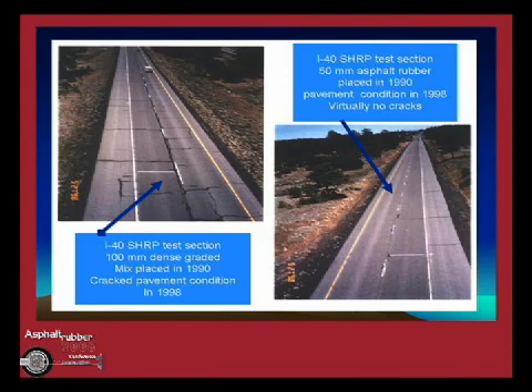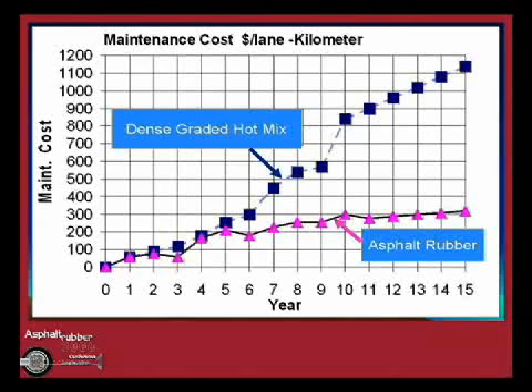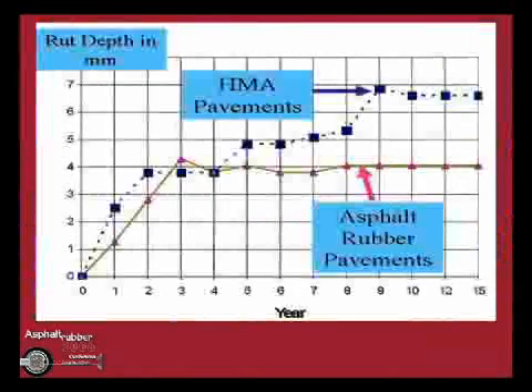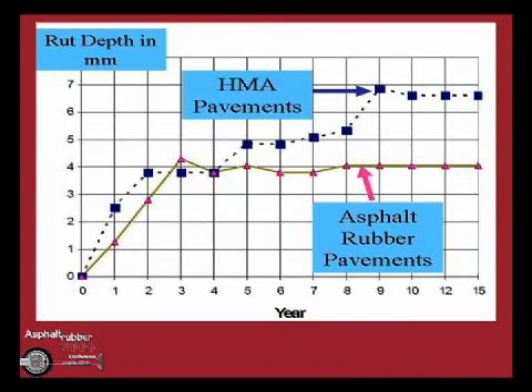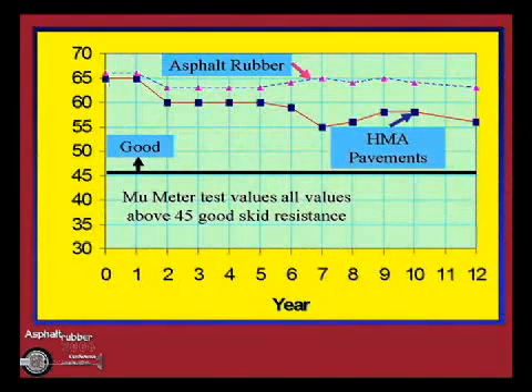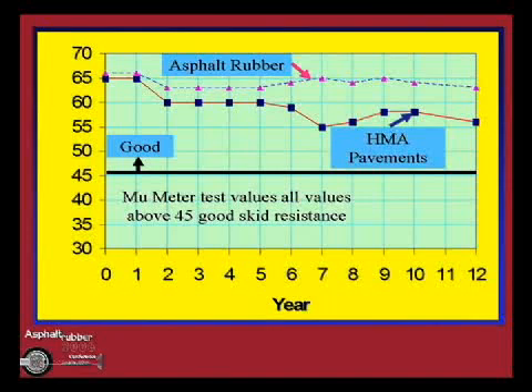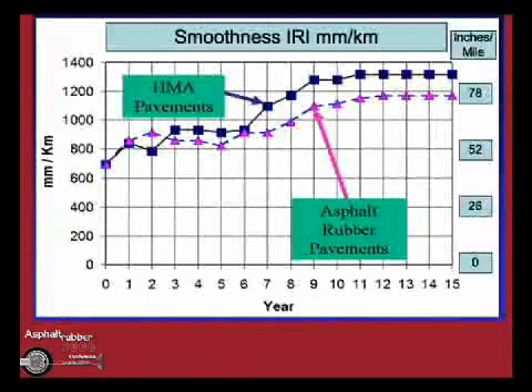Maintenance costs, another reason why we've seen this material used widely in Arizona. In other states, it's much less than conventional mixes. And again, this is due to the fact that there's just much less cracking to have to maintain. Rut depth, pretty good. It doesn't rut to a great degree, and that's again because you have a lot of stone-to-stone contact. And then skid numbers, mu-meter numbers, are also quite good. Normally because, again, of that coarse surface texture, the material is a good texture, a good drainage layer. And again, with the dense graded, you have to come back and do maintenance, and oftentimes that means putting more oil on the roadway.